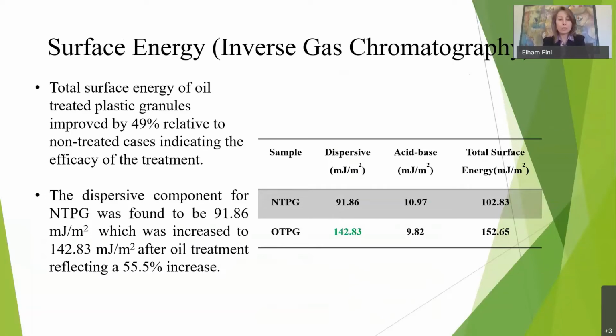And this was a strong evidence or motivation that if we can increase the surface energy by this much, then we should be able to make it like the rest of material and not to separate, not to segregate. So let's see if it worked. So we increase the surface energy with oil treatment by biografting the biomolecules on top of the surface of the plastic. So literally your plastic now is carrying all these biomolecules around it and is not the same as typical plastic, it is basically hosting all these biomolecules on the side of it, around it.